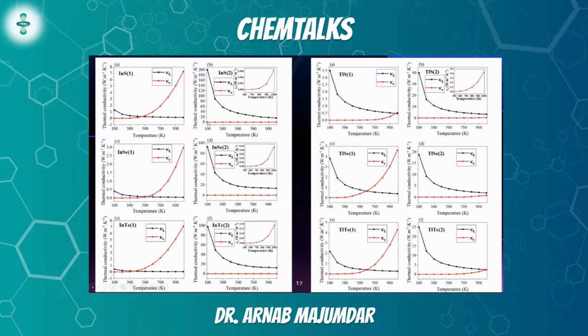At 100 Kelvin, for InS2, the thermal conductivity, kappa L, the black line, was 200 watt per meter per Kelvin. The same for AX1 or INS1 was barely more than 1. So it was almost 150 to 200 times lesser. And you'll see the same trend for all these graphs, whether it's the indium series or the thallium series or even the gallium series, it will always be the same.